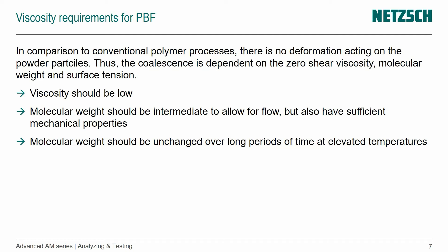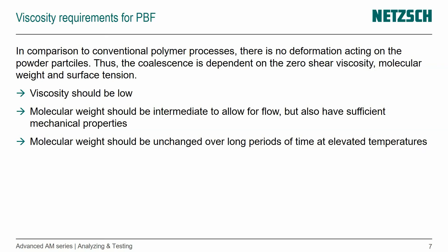The molecular weight should be not too high and not too low. We want it on the lower side so the viscosity is low, but we don't want the molecular chains to be too short, otherwise the mechanical properties of our final part are low. So we need a balance there. But we also want that molecular weight to not change or change as little as possible over the long periods of time at elevated temperatures. And we want to understand that, obviously.